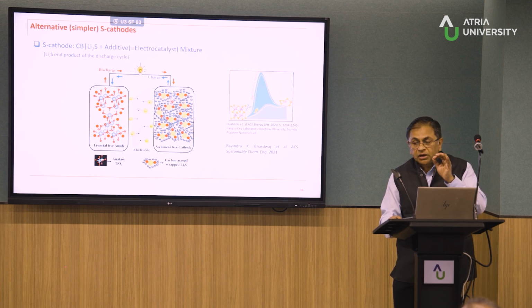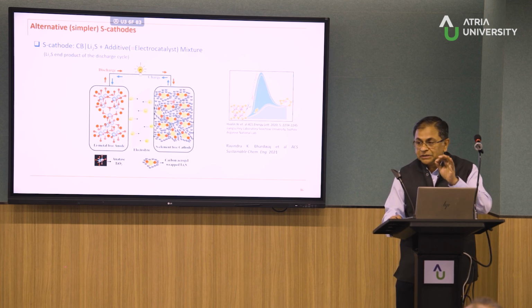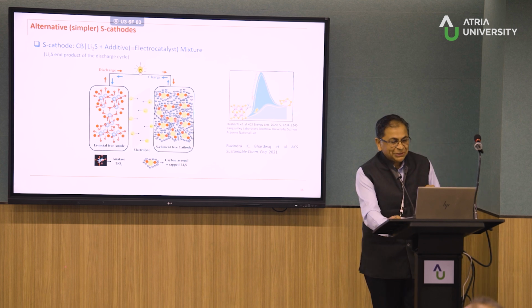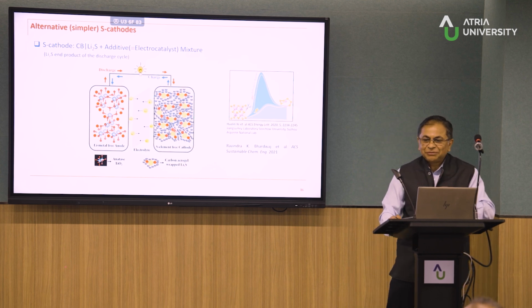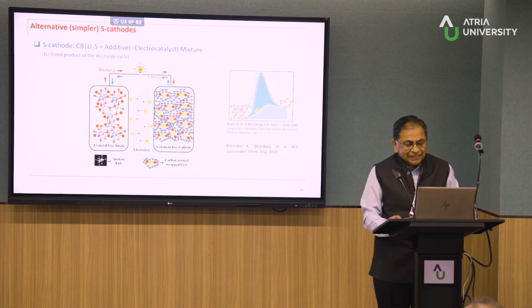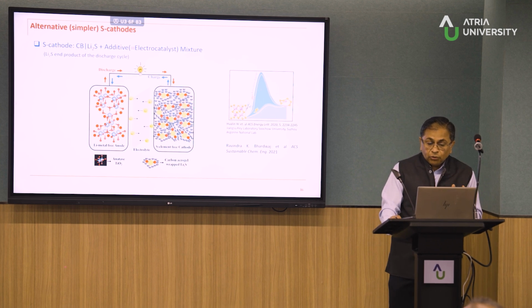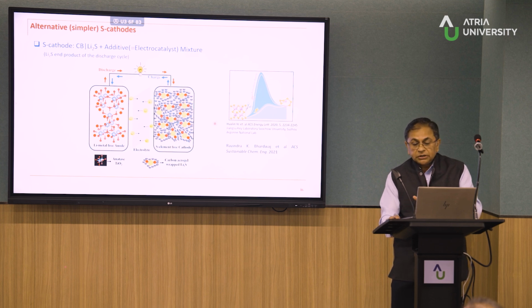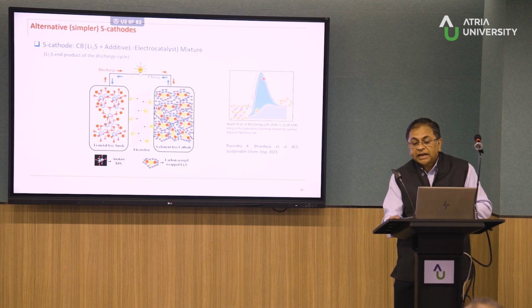The only problem is if you don't have a good clean room, lithium sulfide is very hygroscopic. So you need a clean room. That's why the students always have to make cells inside a glove box. The other problem is that now you're going from sulfur to an ionic compound, so you have this problem of an activation barrier.